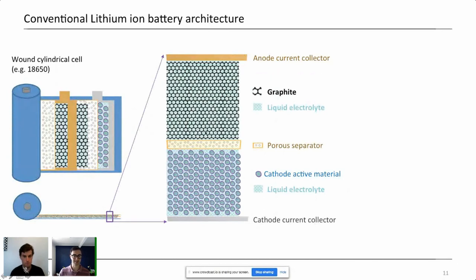the active particles. The middle layer of this sandwich here is a porous separator. So this is just a plastic sheet. Think about a saran wrap that you might have in your kitchen, but it's been stretched to be thin and also to tear. And it's made deliberately porous so that the liquid that carries the lithium ions can go through these pores from the top to the bottom compartment.